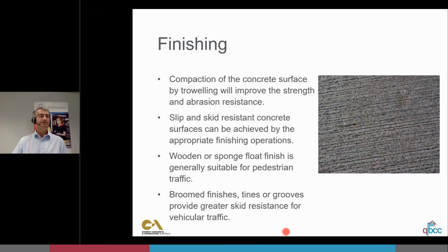So finishing. Finishing is very important, as I said earlier, for densifying that surface, giving it some resistance to wear and dusting. This looks like a broom finish. But if you're going to do a broom finish, you still need to make sure you densify that surface and get some strength there before you apply that broom finish with a stiff broom. It talks about compaction or densification of the concrete surface by troweling, and the appropriate finishing operations such as brooming or wooden or sponge float finish to avoid a slippery finish. And then the broomed finish comment down here.